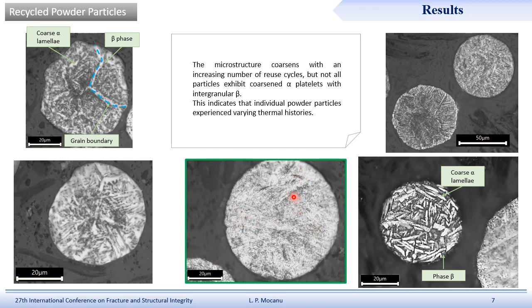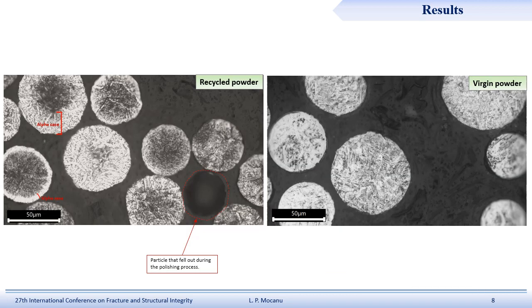This is more similar to the virgin powders, and this is due to the fact that each powder particle experienced a unique thermal history, and this is true because some particles are closer to the melt pool, while other particles are far from the melt.